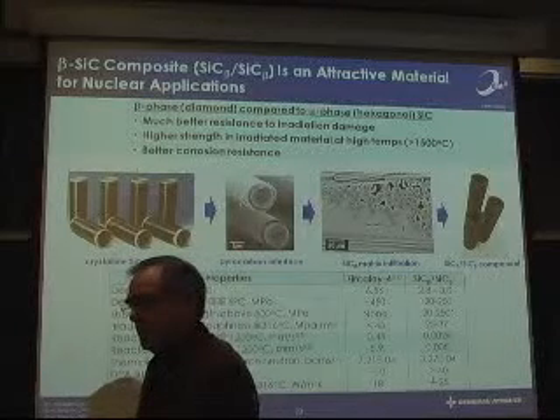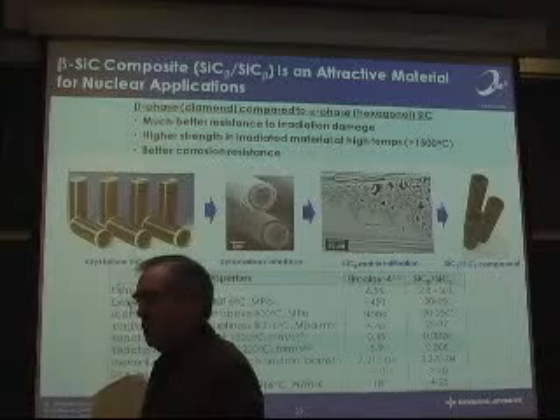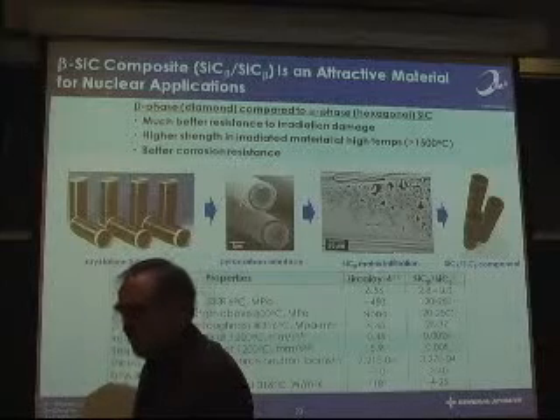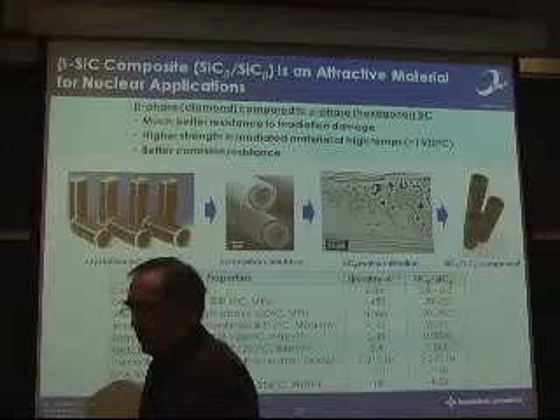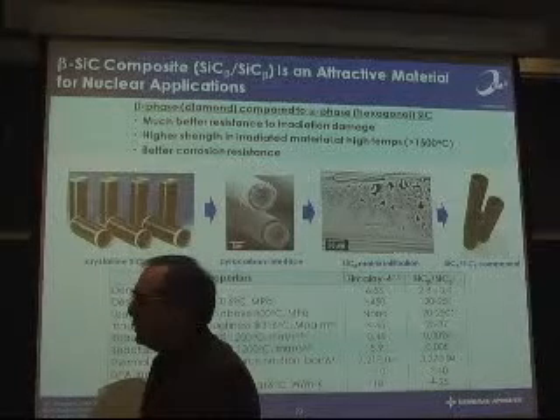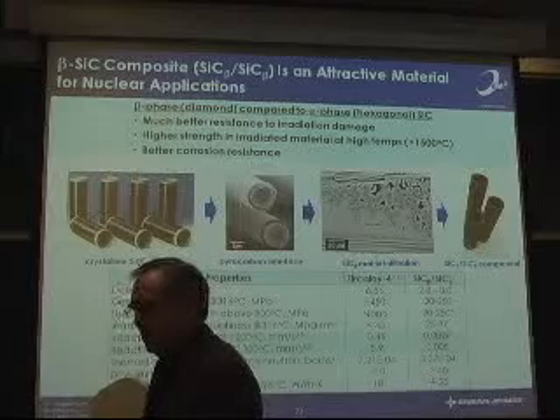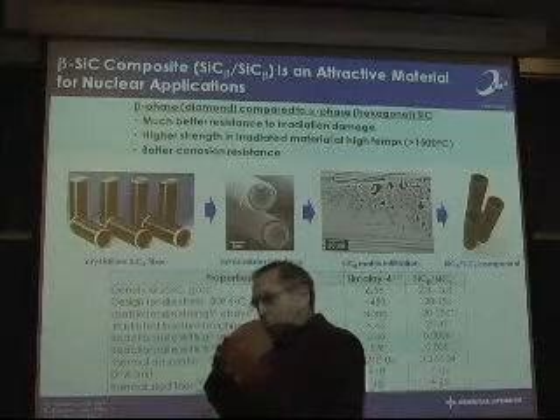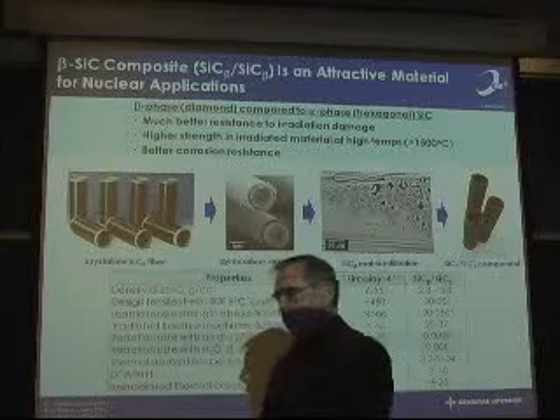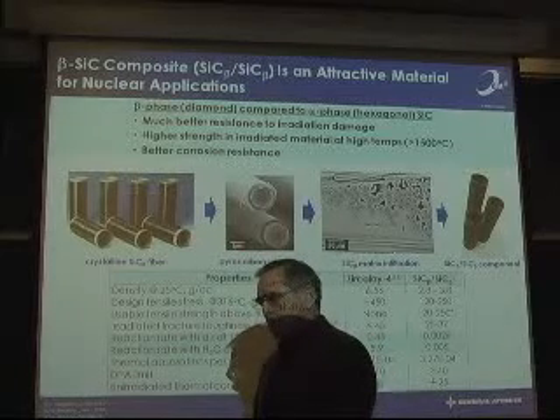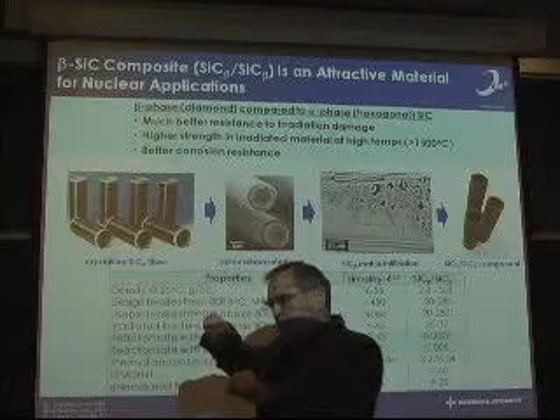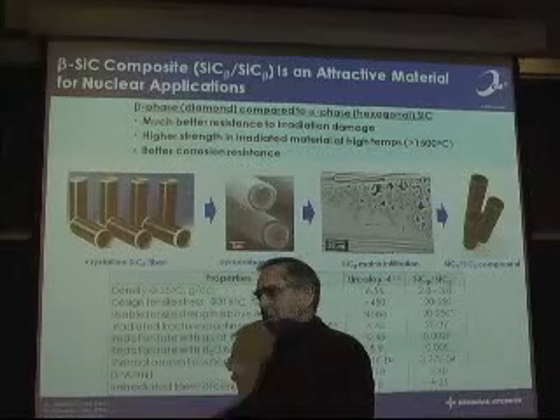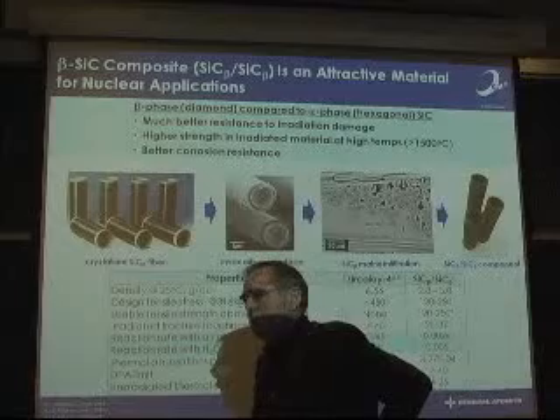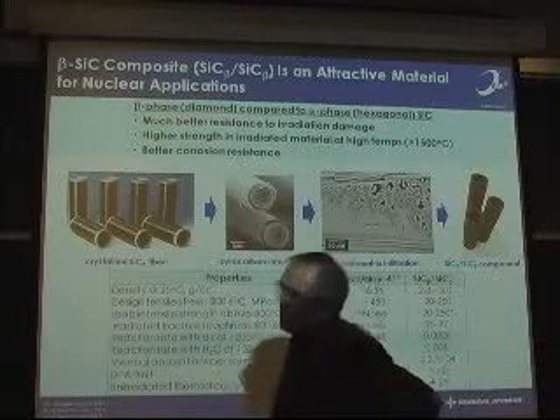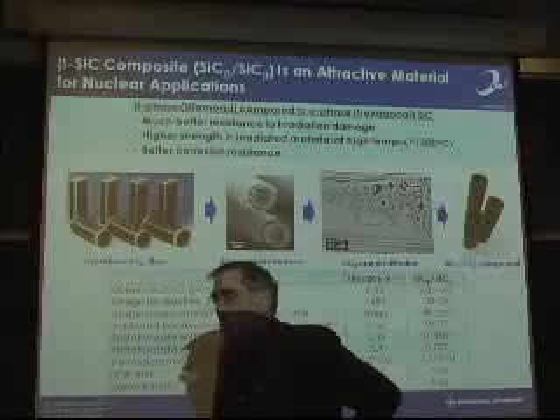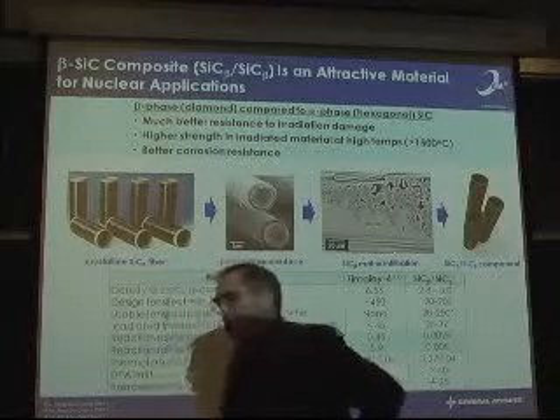Oh, yes. At temperature, the silicon carbide composite is as strong as the zircaloy. Well, you call it quasi-ductile. When you make the composite with fibers infiltrated with material, it is able to transfer the loads to the fiber, and you get a little bit of ductility, but a great deal of fracture toughness, such that the fracture toughness of the composite is very close to the zircaloy, but you give up a little strength when you do that.